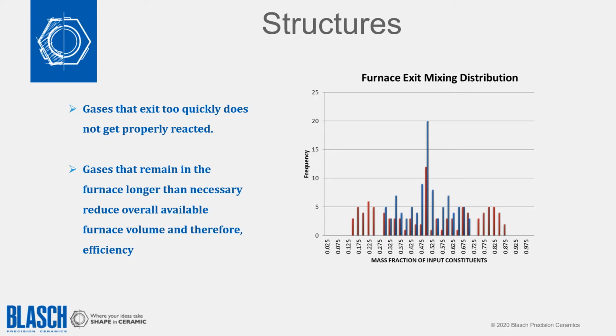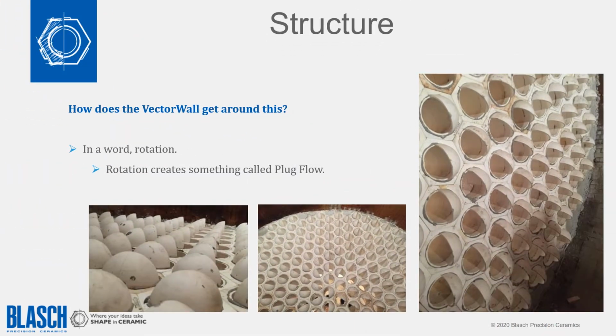The red is a choke ring type of configuration where you have a percent of the material exiting very quickly. That's the material that goes straight through the middle. It gets a little boost from the venturi, and it's out of the furnace well before there's time for it to mix, much less react. The little section to the right is gases that have been rejected by the choke ring and have come back toward the burner, or back mixing. They're in the furnace for much longer than necessary. And then in the middle, you've got the range at which the more or less optimal residence time exists. So you can see that it's much broader, much more spread out, and further away from ideal residence time. We talked about rotation and plug flow. That's what's occurring here.